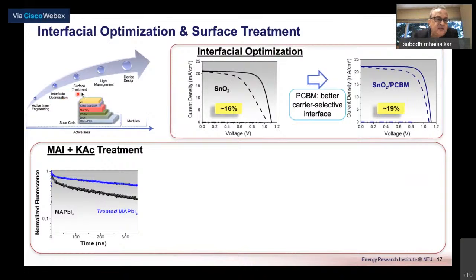After that was done, a surface treatment was needed. The identified surface treatment included methyl ammonium iodide as well as potassium acetate, and this allowed really to compensate, to neutralize a lot of the defects that were present in the bulk perovskite.